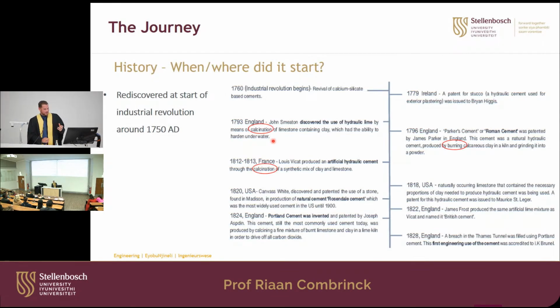If you look at some of the early mixtures before it was patented, it all had to do again with taking limestone and clay and calcining it, in other words, burning it at a high temperature. And it was only in 1824 that, I think, an English bricklayer, Joseph Aspdin, patented Portland cement. And this is the cement that we still use today. It's produced by taking a fine mixture of limestone and clay and burning it at very high temperatures, up to about 1,400 degrees Celsius. And you need to get rid of all the CO2, which is also one of the issues with cement, but that is the CO2 that comes off, and that makes it a very, very strong cement.